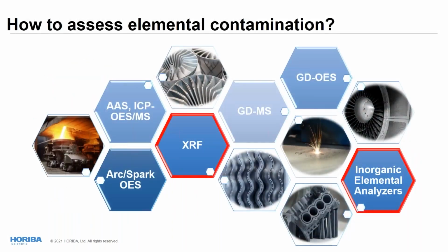There are many different techniques available for elemental analysis. You can have ICP-OES, ICP-MS, GDMS, GDOES. They all have advantages and drawbacks, but the most suitable for additive manufacturing are X-ray fluorescence, or XRF, and inorganic elemental analyzers dedicated to carbon, sulfur, oxygen, nitrogen, and also hydrogen analysis. Those techniques are also described, as Anderson was showing, by ASTM methods related to additive manufacturing, which greatly facilitates their implementation in your processes.